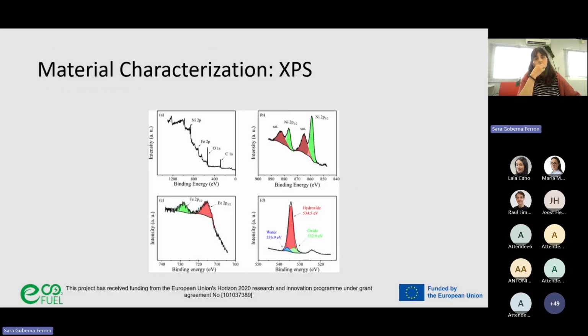Other characterization that we did was XPS. By XPS, we basically confirmed the presence of all the elements in the samples, but also we can confirm the oxidation state of nickel, which was assigned to nickel 2+, iron 3+. And here in the bottom right, we have the spectrum of oxygen, where we observe basically the main peak of the hydroxide, and then two small contributions for oxide and adsorbed water.